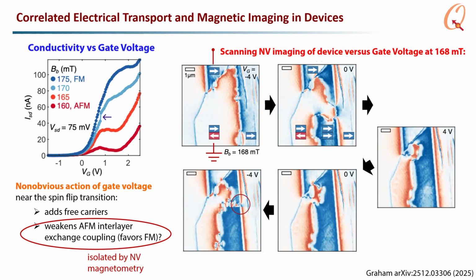And what's happening here is that as you dope the sample, the interlayer exchange coupling changes to be less antiferromagnetic. So at finite field, it favors the ferromagnetic state. And this is partially reversible. As I decrease the gate voltage, the ferromagnetic regions now recede and move back. So these are things that you can do with NV centers that give you additional information that's not obvious to transport.